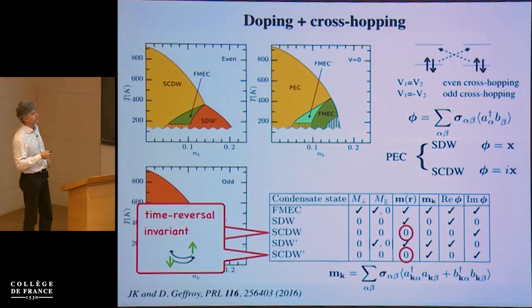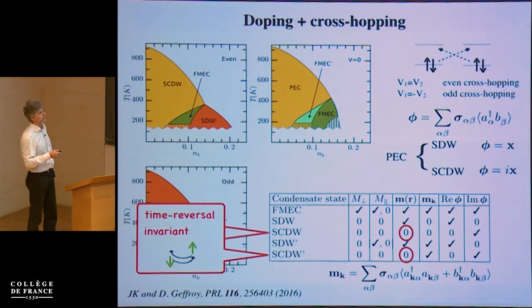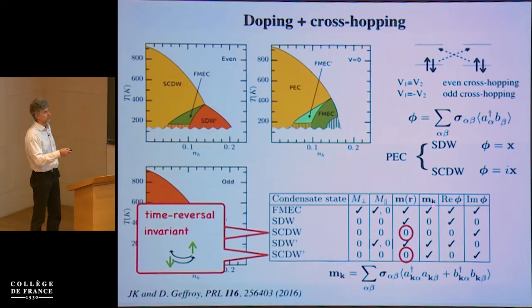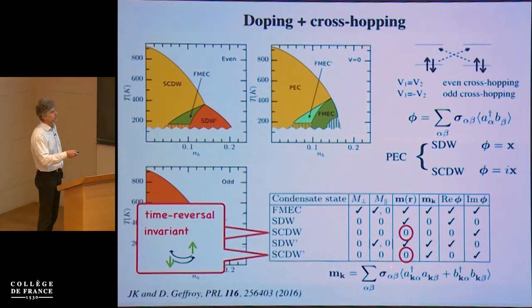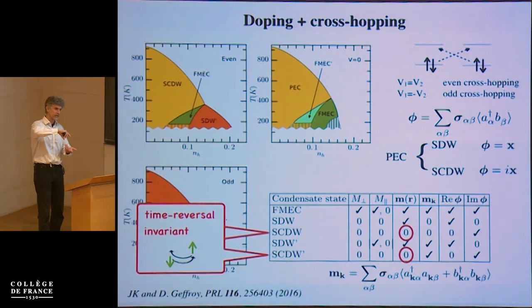And we still have two different types of these phases. You see, there is no magnetization in real space, then of course no ordered moment, but we can still distinguish these two by asking: can we see something if we look in the K-space? In this SCDW phase, there is nothing in the K-space. It means that these spin currents that are now flowing in our system are purely local.